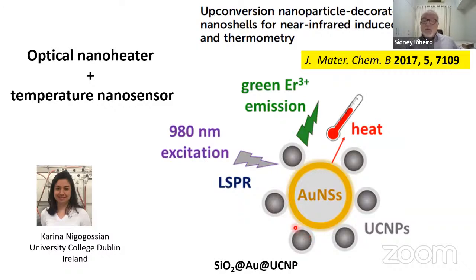Interesting properties are observed here, because when you shine in the infrared at 980, you will excite the plasmon of these gold nanoshells. So you will heat locally the particle. When you heat it, you can measure the temperature by the emission of the upconversion nanoparticles. So what we have here is an optical nanoheater together with a temperature nanosensor.